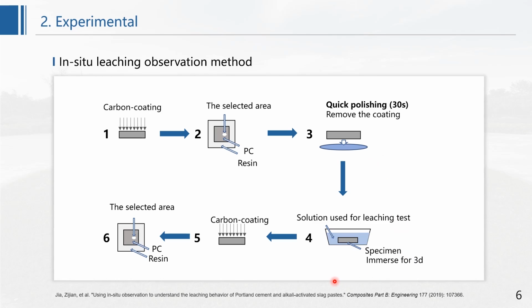After the surface treatment, the sample is immersed into leaching solution for 3 days and then dried in the vacuum oven. After the drying process, the surface of the sample is coated with carbon again. Finally, we will use BSE and EDS to in situ analyze the areas which have been selected and marked in step 2.